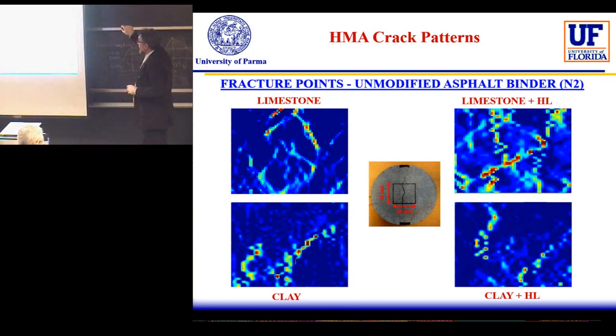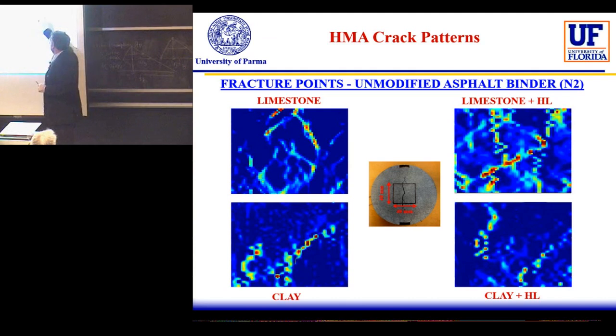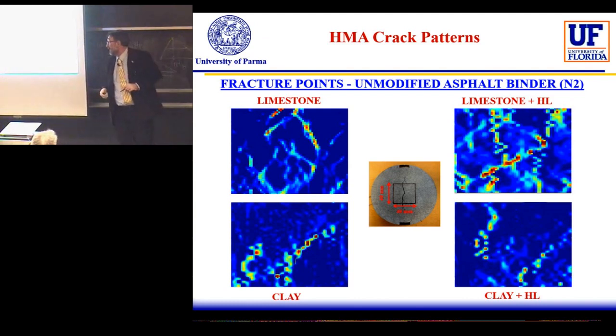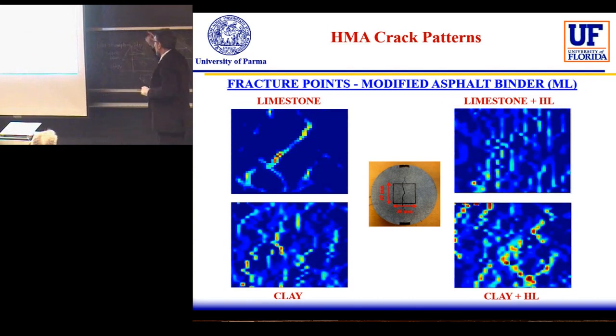And adding an active filler, hydrated lime, to the same ones, we have more difference in one case than in the other. So the hydrated lime combined with clay does not have the same effect on the crack pattern as the hydrated lime combined with the limestone. Here, another difference is made by the different bitumen.